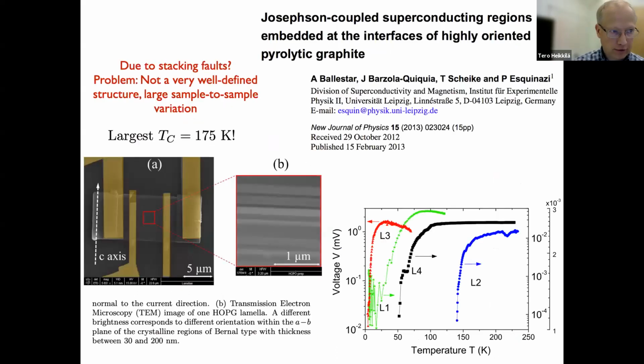And I should mention this experiment. This is already 8 years old, from Pablo Esquinazi's group in Leipzig, where they took highly oriented pyrolytic graphite, and where they knew that there were internal interfaces between different orientations of the graphenes, and they found that systems that contained these interfaces had a superconducting transition, or at least a transition to a zero resistance state at very high temperature. So it could, or maybe could not, be explained by this twinning boundary mechanism. The problem is that we don't really know what is going on in those experiments, what happens in the structure. And there are very large sample-to-sample variations.